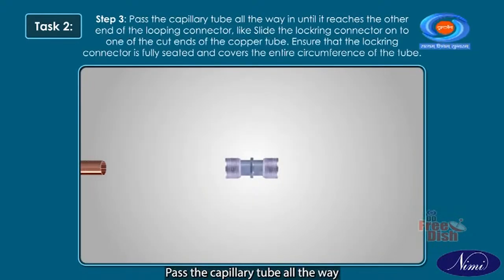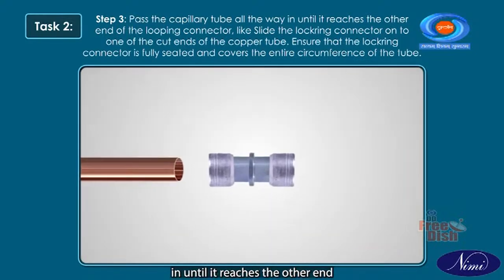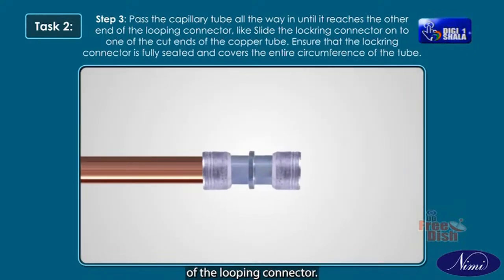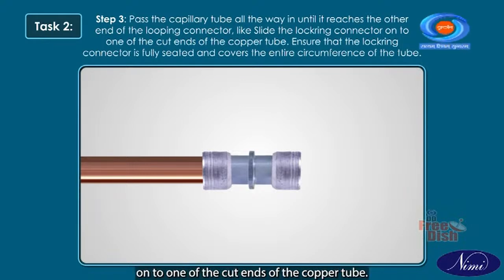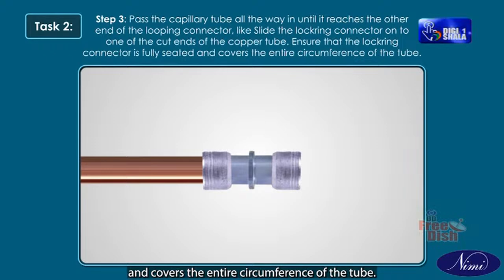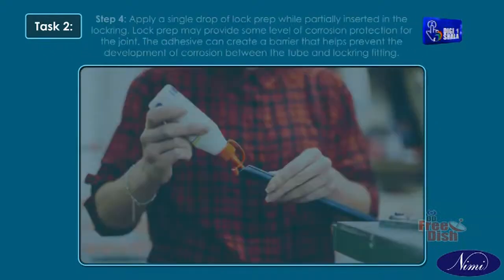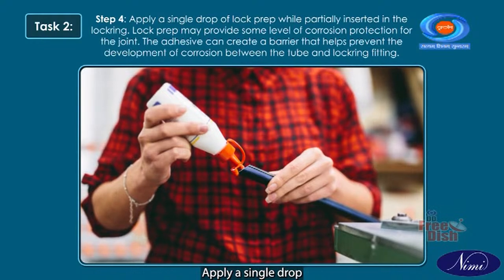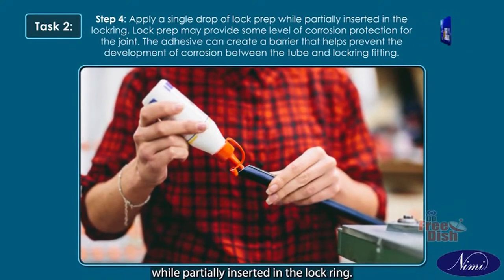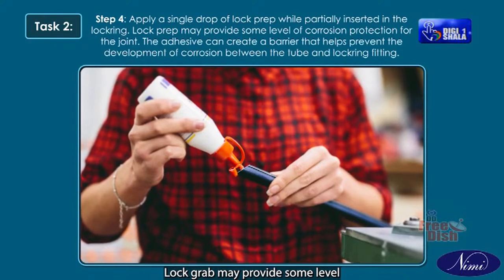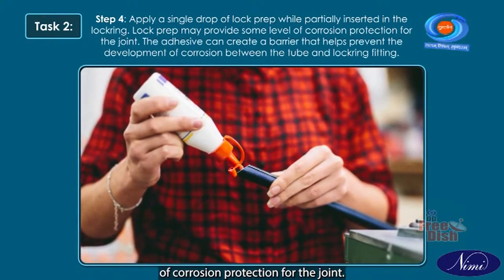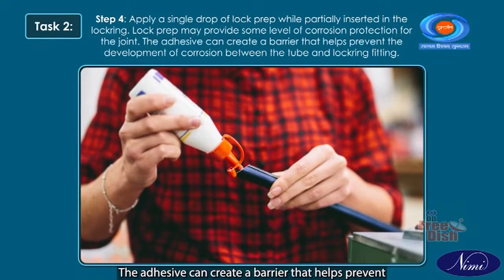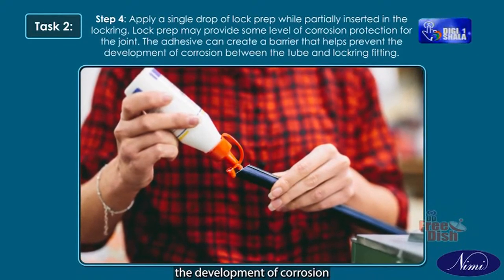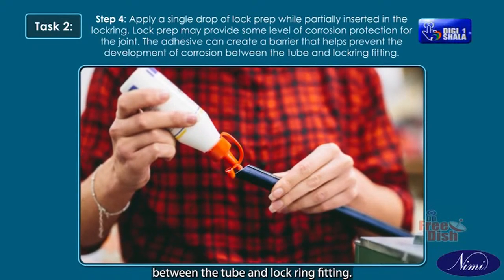Step 3. Pass the capillary tube all the way in until it reaches the other end of the lock ring connector. Slide the lock ring connector onto one of the cut ends of the copper tube. Ensure that the lock ring connector is fully seated and covers the entire circumference of the tube. Step 4. Apply a single drop of lock prep while partly inserted in the lock ring. Lock prep may provide some level of corrosion protection for the joint. The adhesive can create a barrier that helps prevent the development of corrosion between the tube and lock ring fitting.